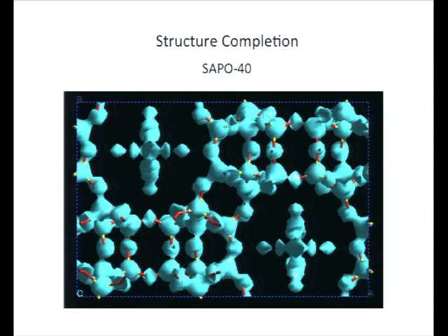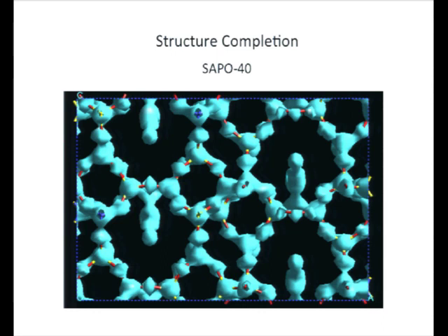There it is. The framework is buried in here in electron density. We're supposed to have subtracted that out. Here's what we're looking for. In order to find it, I had to reduce the electron density contour level quite a long way, as these electron densities on the framework itself are stronger than this one. If we look at it from the other side, it looks like that.